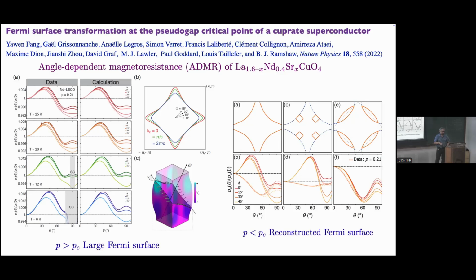Oh yeah, what I was going to say is, photoemission depends on what's called the quasi-particle residue. So you could imagine a situation where the quasi-particle residue is large in the front and very small at the back, and that would explain the photoemission. On the other hand, ADMR, where you're not taking any electron out of the sample, doesn't care about the quasi-particle residue. So it's not insane that there could actually be a backside, because it's independent of the quasi-particle residue.